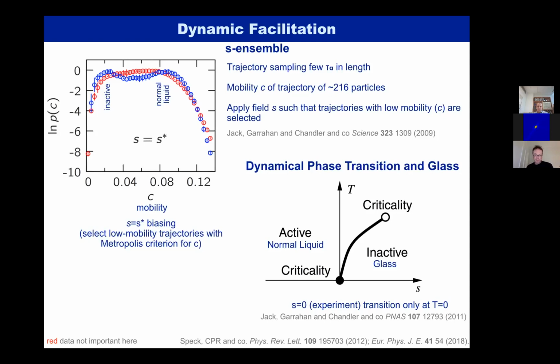So the dynamic facilitation picture of this phase coexistence imagined that there are fast-moving trajectories and slow-moving trajectories. If you recall, a trajectory is a small number of particles, in this case 216, which is sampled for a short time, a few alpha relaxation times of the system in length. Shown in the graph on the top left is evidence for this phase transition in particulate data, in particular a Lennard-Jones model of a supercooled liquid. We see there are two peaks. There's the inactive phase at a low value of C and the normal liquid at a high value of C. And these two distinct peaks are very much what the theory predicted.